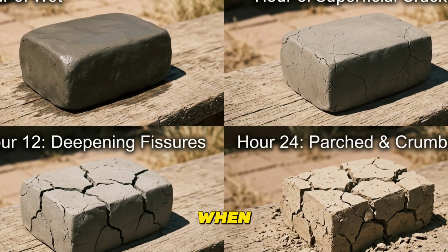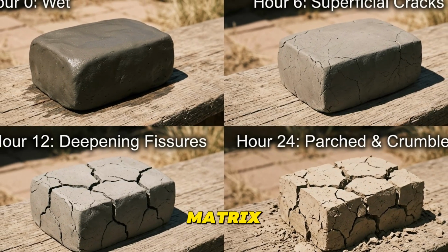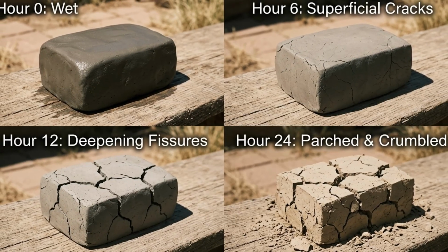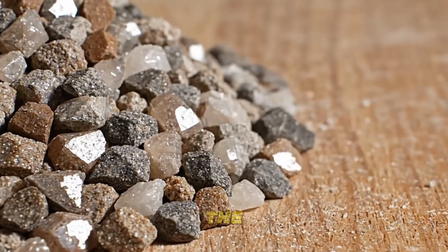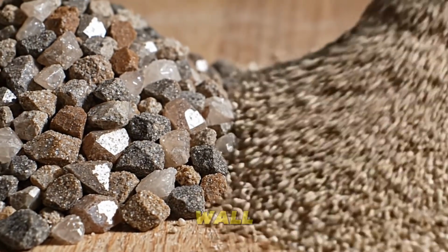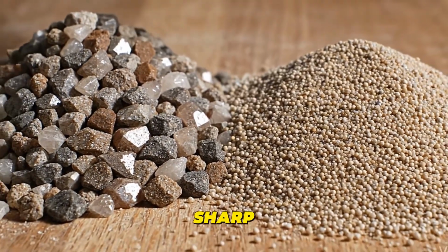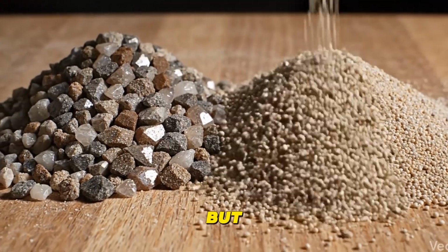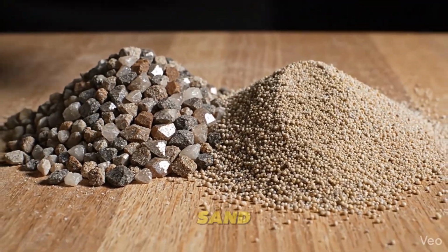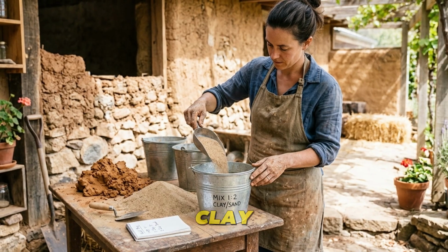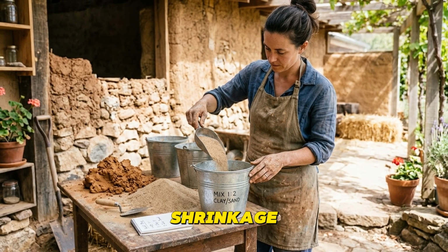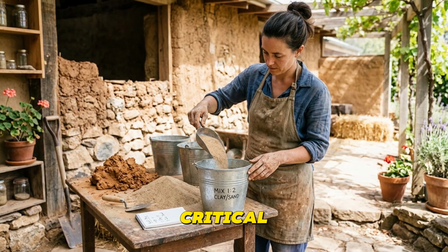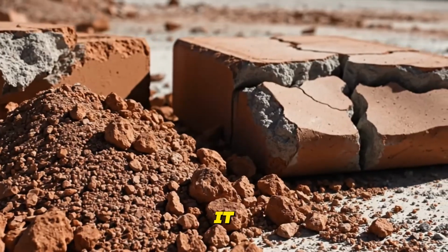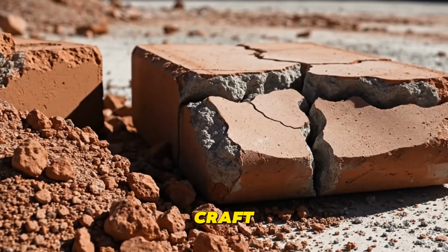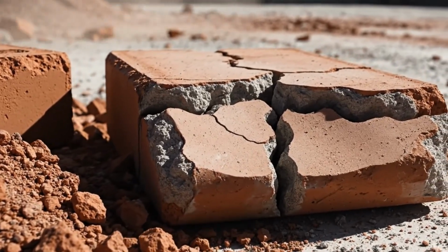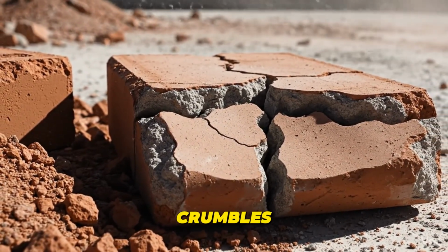Clay alone shrinks when it dries, because the water leaving the matrix causes the clay plates to contract. Without aggregate to maintain the volume of the material during drying, a pure clay wall would crack severely. Sharp sand, not rounded beach sand, but angular quarry sand or sharp river sand, interlocks mechanically within the clay matrix and resists shrinkage. The ratio of clay to sand is the critical variable in cob mixing, and getting it right is the foundational skill of the craft. Too much clay and the wall cracks. Too much sand and it crumbles.